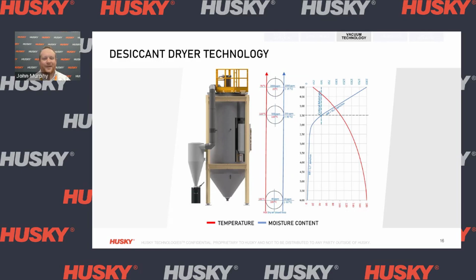Now, what I'd like to do is go even deeper into the technology of both a desiccant-based dryer and a vacuum dryer, showing you exactly what's happening as the material flows from the top to the bottom of the drying process. So on this graph here, this is a desiccant-based dryer that I'm showing on the screen, and I'm tracking the temperature and moisture content as material flows from the top of the hopper to the bottom. So over the course of 6 hours, as shown on the screen here, we see the material starting off at room temperature, or around 20 degrees Celsius, with a humidity level of approximately 2000 ppm of moisture. If we look at temperature first, the red line, we see a fast increase in temperature early on, where it slowly drops off in temperature as it approaches 180 degrees at the hopper outlet at the bottom.